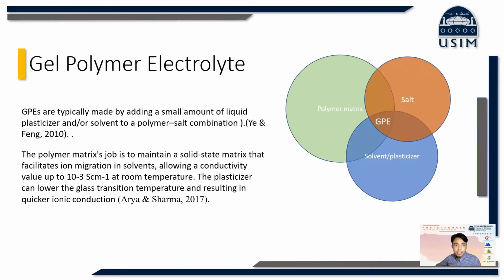Next, gel polymer electrolyte is typically made by adding a small amount of liquid plasticizer and or solvent to a polymer salt combination. The polymer matrix's job is to maintain a solid state matrix that facilitates ion migration in solvents, allowing a conductivity value up to 10 power negative 3 Siemens per cm at room temperature. The plasticizer can lower the glass transition temperature, resulting in quicker ionic conduction.